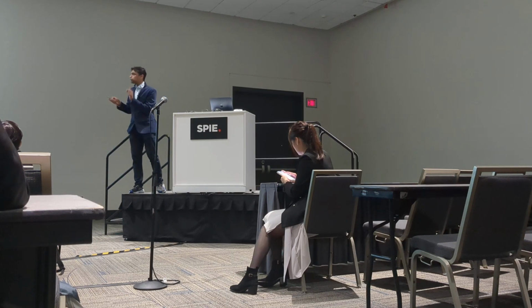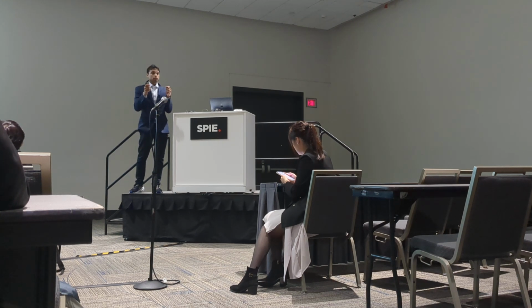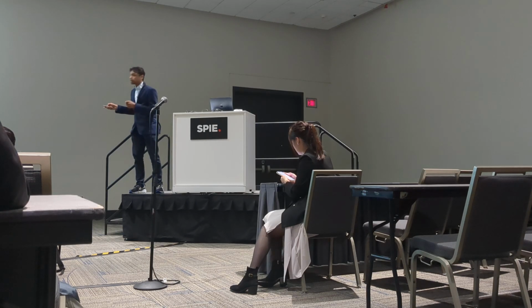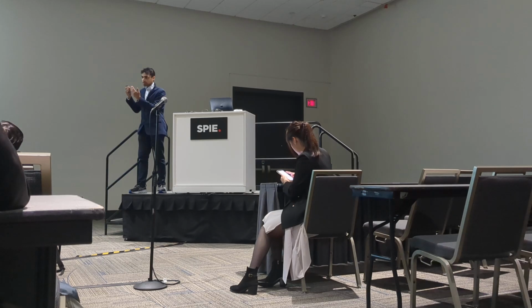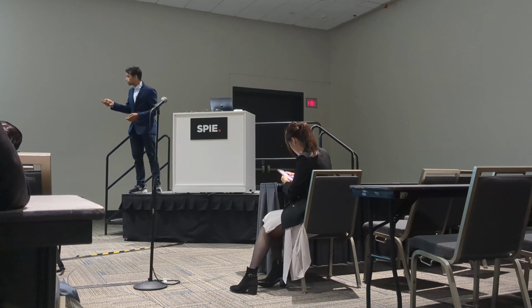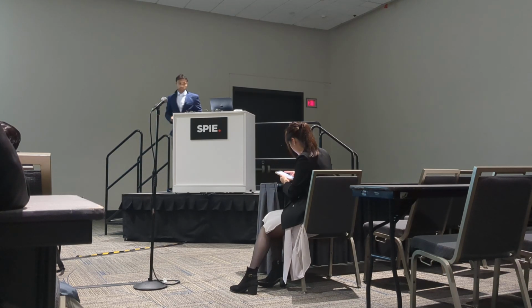Furthermore, to lower this response down to the visible region, we need plasmon hybridization. With plasmon hybridization, if it is an air medium, we still will not reach the visible region, since the UV region starts from 3.1 electron volts. But if we encapsulate it in a high refractive index medium, then we can have a response in the visible region. This is what we have achieved with our structure, and the essential criteria is that the size distribution has to be small and monodisperse, and the particles have to be encapsulated in the PDMS medium.